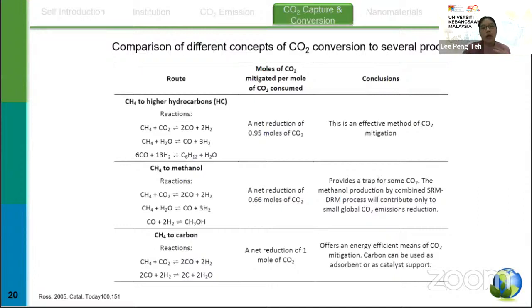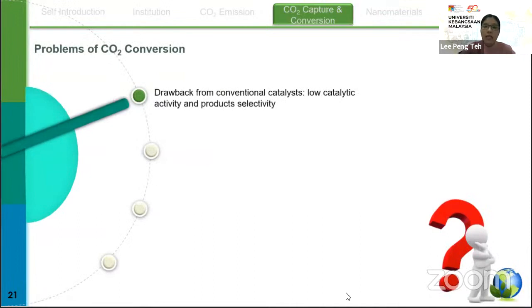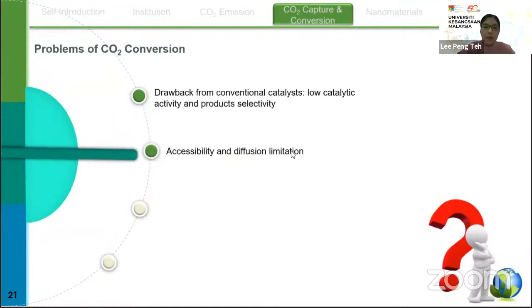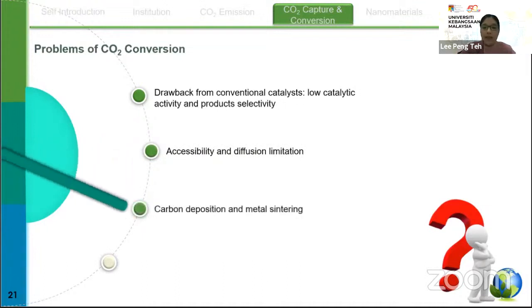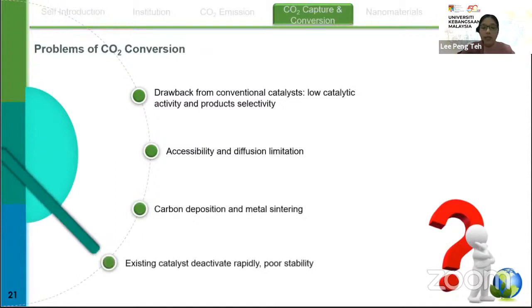But the main problem is that the DRM application itself will produce much carbon formation, which will deposit on the catalyst surface and cause the deactivation of the catalyst, as well as reduce the efficiency of the DRM reactions. Therefore, DRM depends very much on new and stable active catalysts, as well as the price of CO2, right? To conclude, existing catalysts possess several drawbacks such as low catalytic activity and product selectivity, accessibility and diffusion limitations, carbon deposition and metal sintering, and also poor stability because of rapid deactivation.